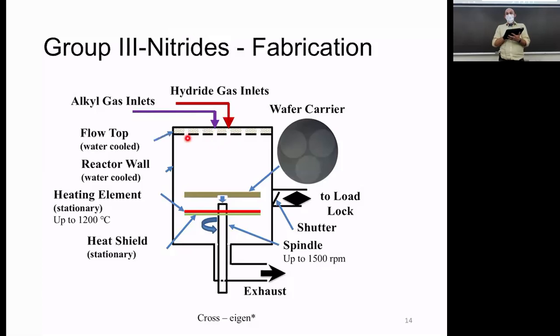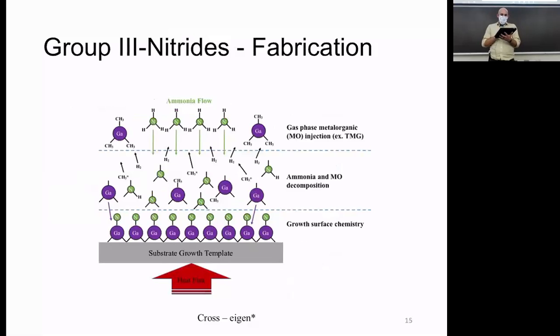It would be cooled at the top so that we didn't get deposition of our material up there. And then it would be heated down here. So this here was heated up to 1100, 1200 degrees Celsius in order to get the chemical reactions to happen that would make these materials. And the way that we did it, we'd bring in our material. So we'd bring in nitrogen with hydrogen, ammonia, and we'd bring in gallium, in this case for this reactor, with a methyl group. So this is called trimethyl gallium. And these chemicals would be brought into the reactor.